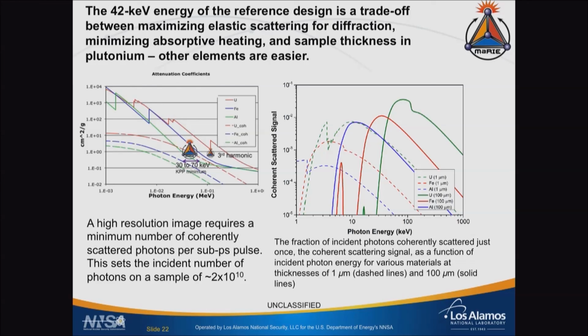And what you want to do is, so this is cross-section for X-ray interactions with matter. And these curves are for different materials: uranium, iron, and aluminum. So aluminum's the lowest one, iron's there, uranium has the higher cross-section. This is the total cross-section, including all the absorption, all the things that basically suck up the X-rays, turn it into heat, and turn it into a plasma.